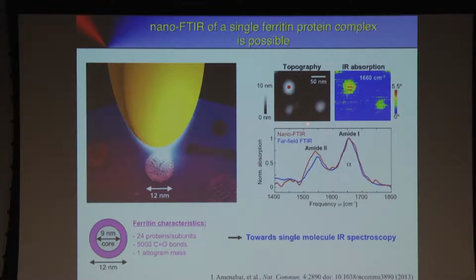That's the topography image. Here we see 3 particles. We placed the tip on the red spot here and took a spectrum. This is the red curve, and we see nicely these 2 peaks corresponding to the amide 1 and amide 2 bands. Then we did a far-field experiment of an ensemble, probably millions or billions of these particles, and we get the blue spectrum. We get a really nice match. So then we can choose a single wavelength, here using a quantum cascade laser. We use this wavelength and then take an image.